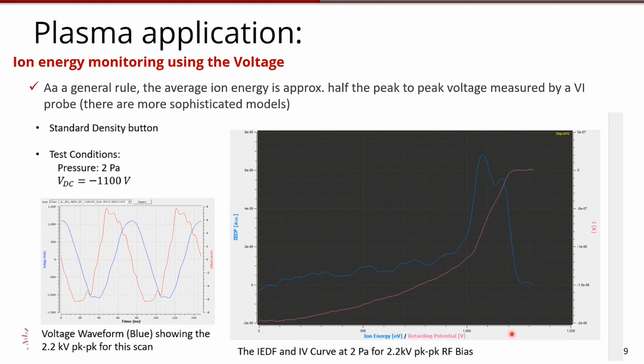For those of you who didn't attend the last webinar, which was all about ion energies and different tools under different conditions, this blue line here is the ion energy distribution function. The bottom axis is not clear, but this is a case where the VDC is measured at about minus 1,100 volts. The ion energies are in and around that value. So this shows how many ions are at different energies, going from 0 to 1,500 eV on this axis. Most ions are at this energy due to the RF bias being applied, and then there's a tail that's caused by collisions at different pressures and so on.